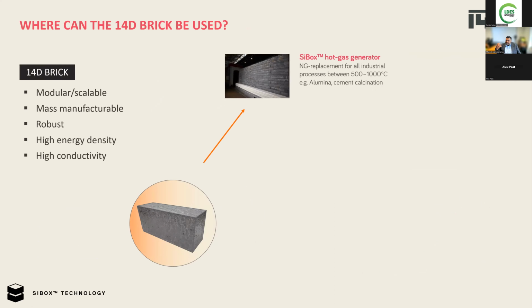Now, where can this brick be used? There are multiple configurations you can use this brick in. The simplest one would be as a hot gas generator. You can stack these bricks up in a certain arrangement, heat them up using resistive heating elements, and then use some heat transfer fluid to extract that energy out when it is needed. And that is the configuration that we've built in our workshop here in the demonstration module. I'll talk about that a bit more later on. But the hot gas generator can act as a replacement for natural gas in a lot of the high temperature industries like alumina and cement. And there were some questions in the chat around the cement and alumina industry as well. So the phase change material we currently use melts at about 1100 degrees or so. So you can go up to 1000 degrees in terms of the outlet temperature from the demonstration module.